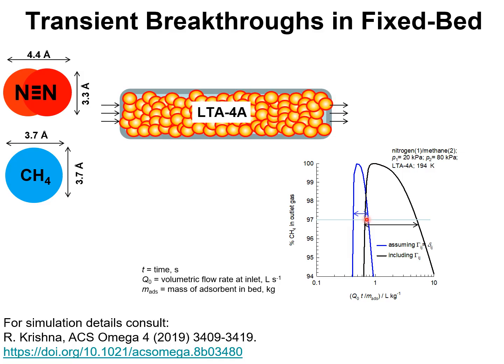We note that for the model in which thermodynamic coupling effects are duly accounted for, we can recover a larger amount of methane that meets the pipeline specifications. Whereas if we ignore thermodynamic coupling effects, the productivity of purified methane is significantly lower.